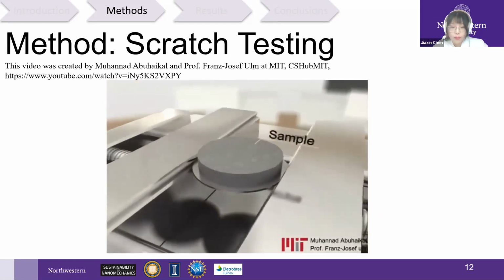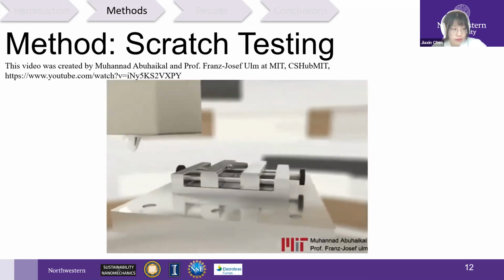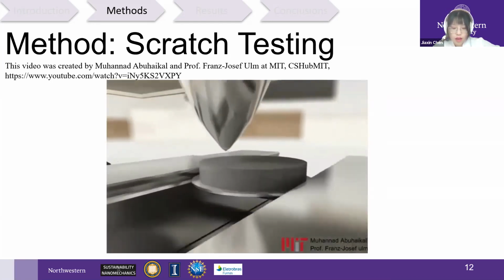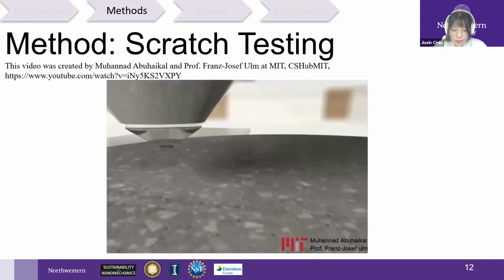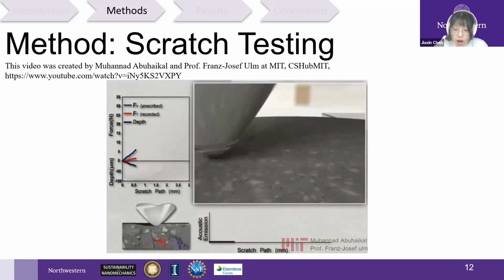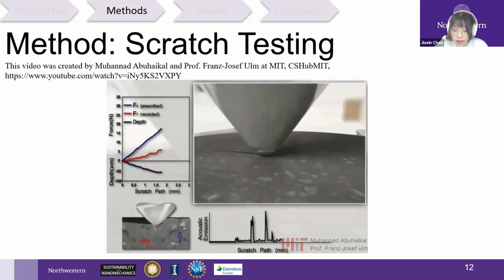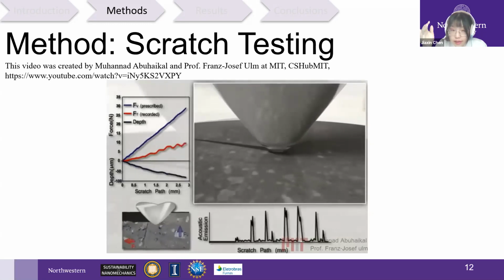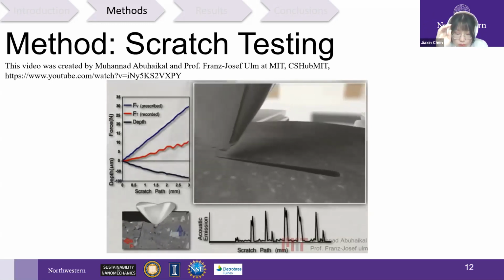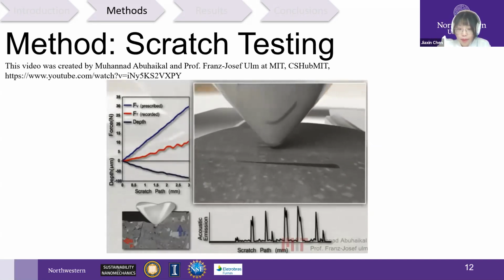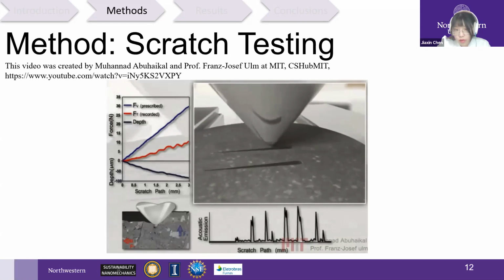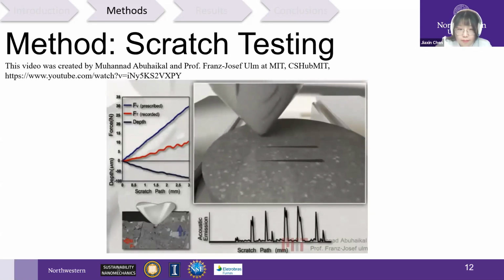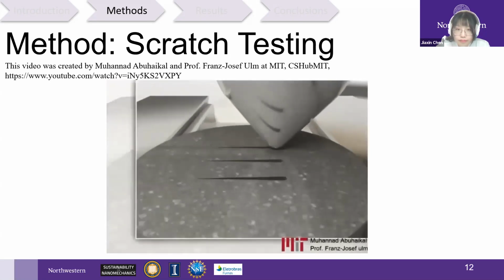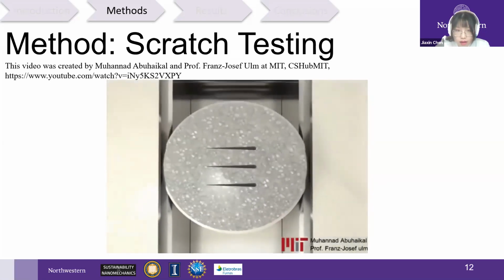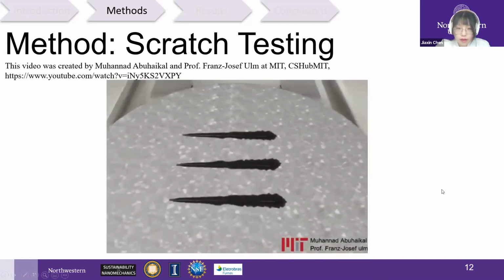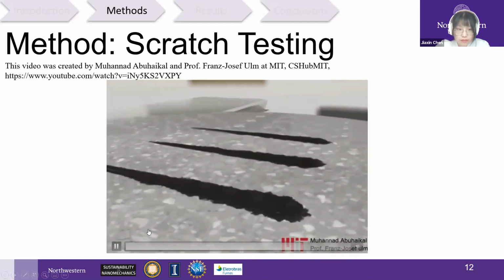So this is the sample. You can see the flat and smooth surface of the sample. And this is a Rockwell tip. The Rockwell diamond indenter was pushed across the surface of the sample material, while linearly increasing the vertical force as shown on the left-hand side. The penetration depth and the horizontal force were recorded as shown here. Here are the final scratched surfaces.